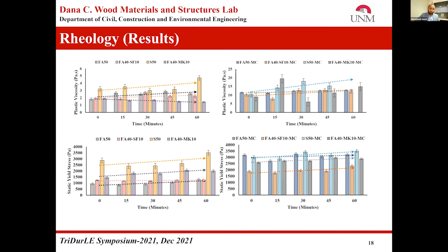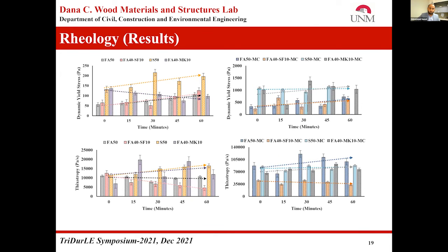The rheology results show that with evolution of time from 0 to 60 minutes, the plastic viscosity showed an increasing trend, and a similar pattern was observed in the case of static yield stress. If we compare the standard ECC mix with the methyl cellulose enriched mixes, with the addition of methyl cellulose, the rheological properties were significantly improved in terms of plastic viscosity and static yield stress. The static yield stress is the maximum stress required to break the material from the solid state to the liquid state. A similar pattern was observed in the case of dynamic yield stress and thixotropy.